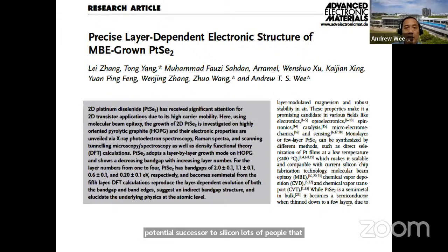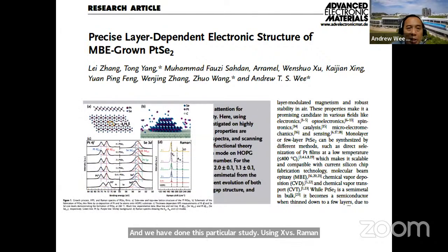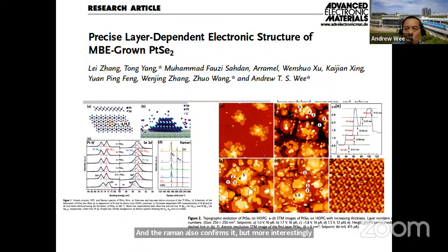We have done this particular study using XPS, Raman, and STM. Here you will see the XPS spectra as you put platinum diselenide on it, which shows we indeed have platinum diselenide. And the Raman also confirms it. But more interesting is the STM. It grows layer by layer, not perfectly. One layer does not complete before the next layer, so there's a little bit of islanding forming. You can see from a cross section integer heights indicating different layers being formed. But on the first layer, you can see a regular structure of the platinum diselenide surface.